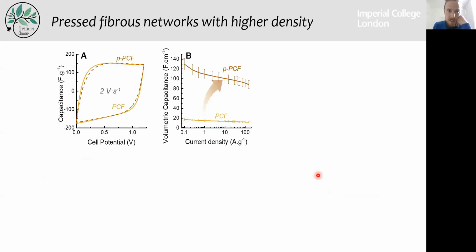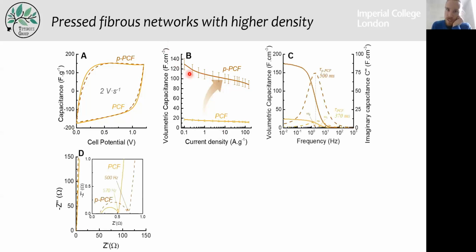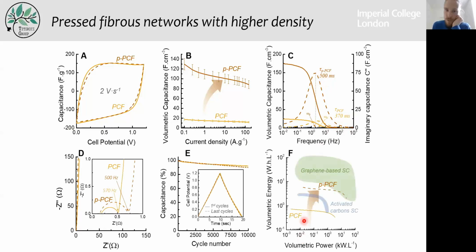And so the last slide. Here you can see that the pressed sample and the non-pressed sample have pretty similar electrochemical performances. But if you look at the volumetric capacitance, which is important because it tells you about the packing ability of your device, it is much, much higher. And if you look at the relaxation time, which is how fast your device can be discharged, it's also very similar. And the volumetric Ragone plot tells us also that the volumetric energy has massively increased.